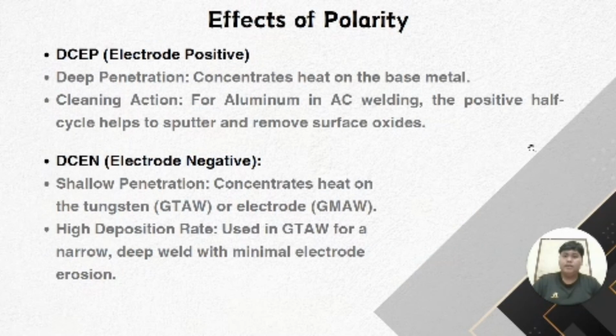Next is the effect of polarity. DCEP, electrode positive: deep penetration, concentrates heat on the base metal. Cleaning action for aluminum in AC welding: the positive half cycle helps to sputter and remove surface oxides. DCEN, electrode negative: shallow penetration, concentrates heat on the tungsten in GTAW or the electrode in GMAW. High deposition rate, used in GTAW for a narrow, deep weld with minimal electrode erosion.